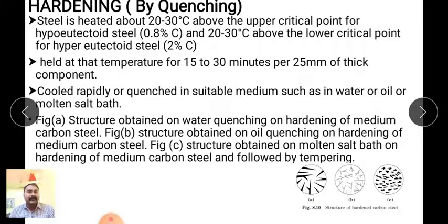In the case of the hardening process for hypoeutectoid steel, we heat that component above the upper critical temperature by 20 to 30 degrees Celsius, and in case of hypereutectoid steel we heat that steel component above the lower critical by 20 to 30 degrees Celsius, and hold that temperature for 15 to 30 minutes per 25 millimeter of component thickness.